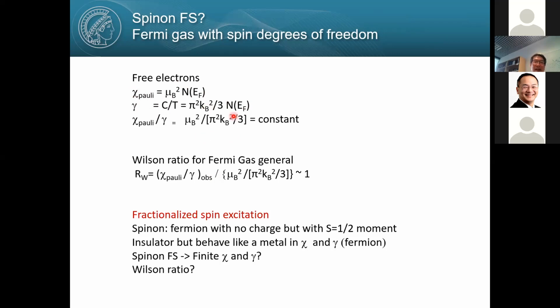So this is called the Wilson ratio. Therefore, when we take a look at a metal, we take the ratio of Pauli susceptibility and gamma, the T-linear coefficient, divided by this material-independent constant. And one means what is expected for this relationship. And in most metals, this ratio is on the order of 1. So this comes from the finite density of states at the Fermi level and the presence of a Fermi surface.